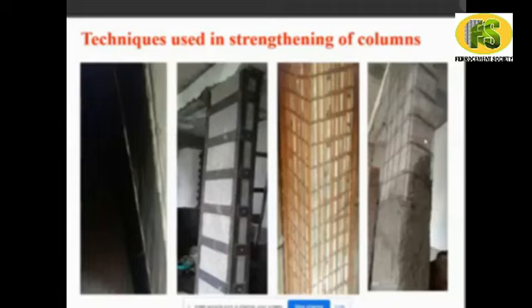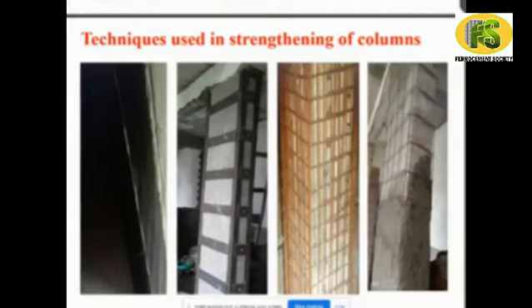And over that, we tied the chicken mesh. The chicken mesh was half inch. Only for the outer side, because inside the concrete is there. So 3 layers were applied from outside, and 1 layer of weld mesh was also there. And before mortaring, we used a bonding agent from Fosroc. We applied the bonding agent, and then mortar was applied.